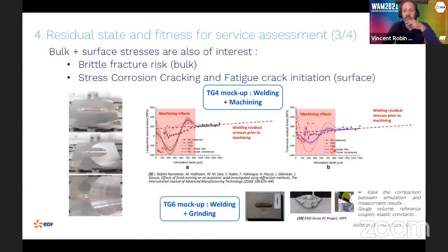Yes, I would like to say a few words about fitness for service of components. We have to prevent our components from cracking, and damage in service can come from brittle fracture, from fatigue, or from corrosion. And we are not only interested in residual stress in the bulk, but also in residual stress on the surface, because generally the welds are machined or submitted to grinding. And that's the reason why we also want to develop some modeling and diffraction measurement approach that can catch the residual stress close to the surface that may affect the residual stress due to welding.